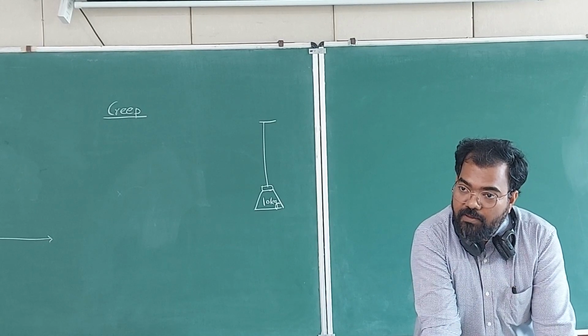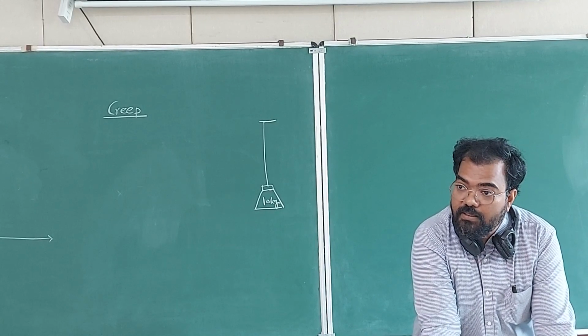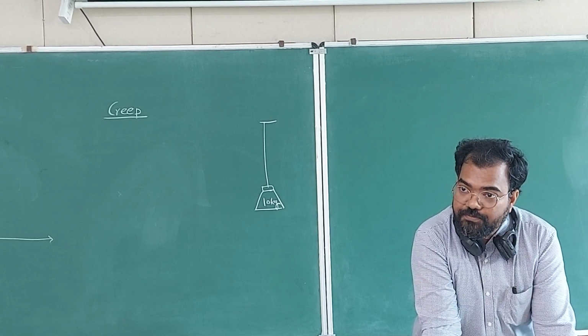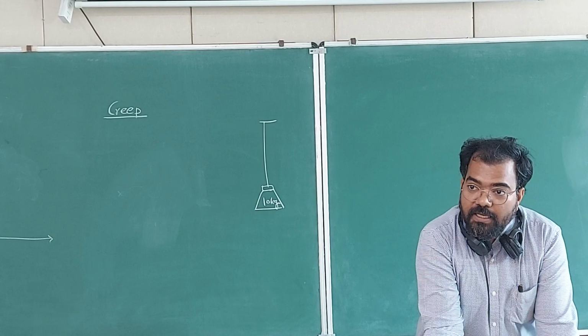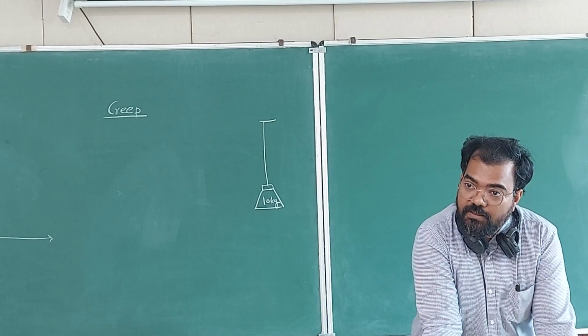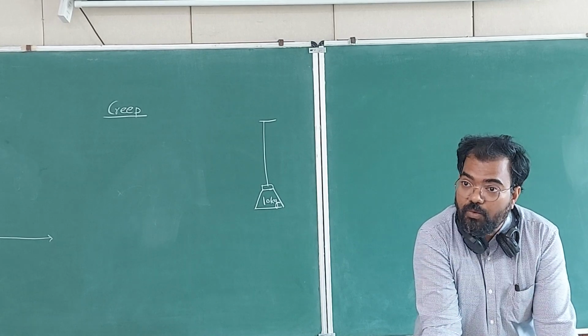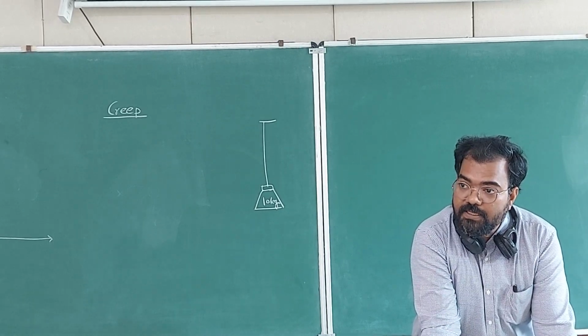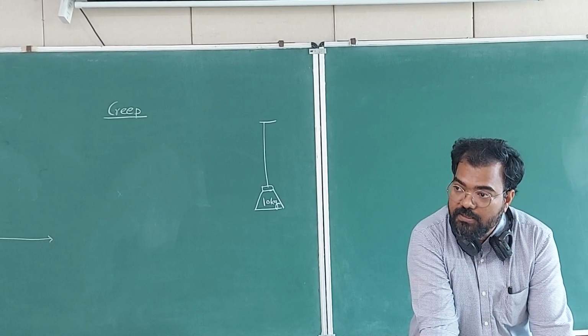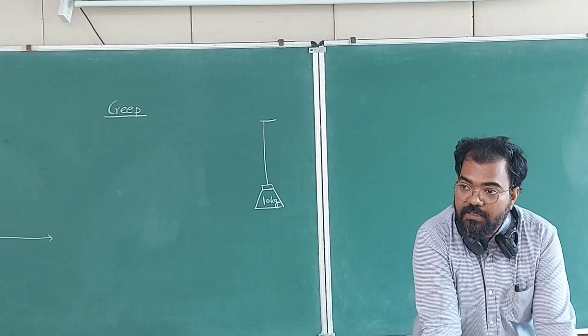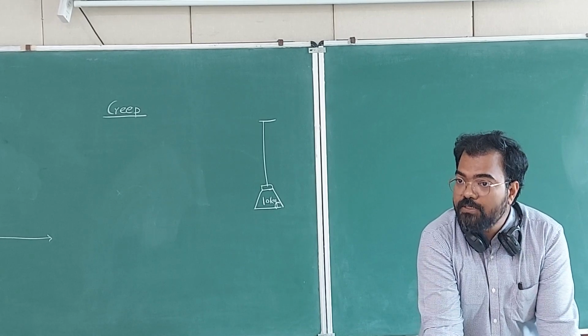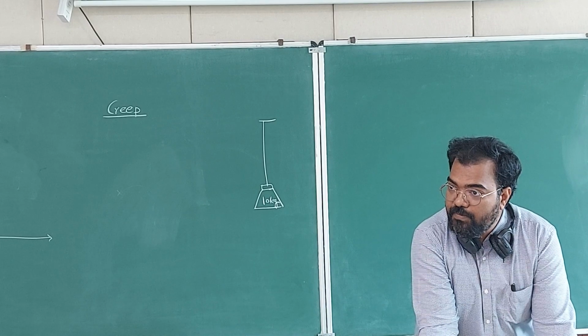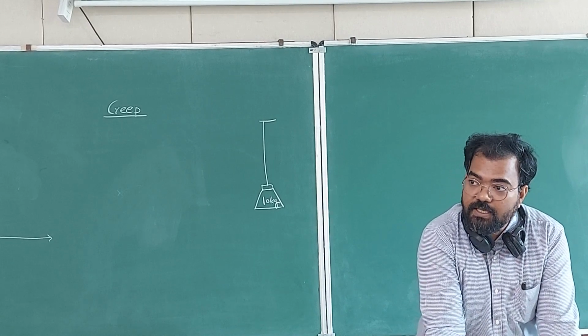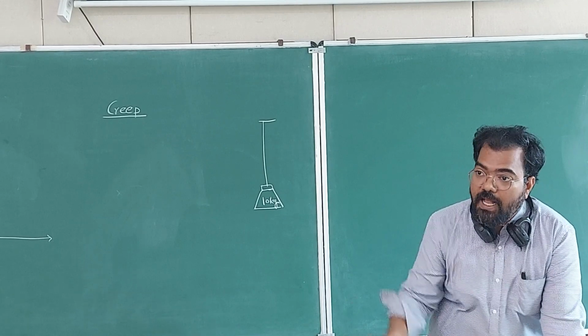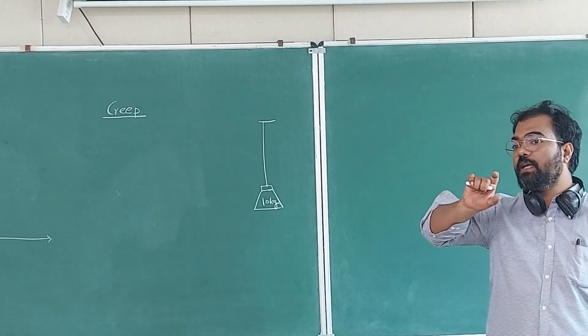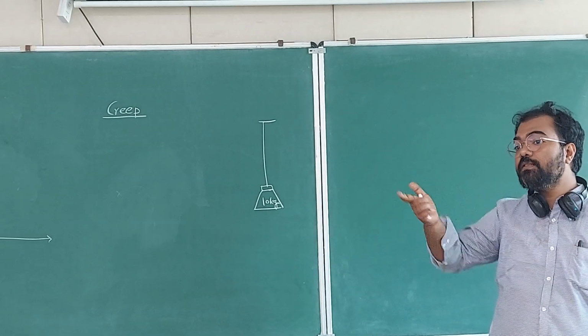Okay, and the second phenomenon will be happening when you facilitate diffusion. Okay, so vacancies do not need stress. That stress is there. They just have to go to the dislocation, and with increase in temperature, you are increasing the equilibrium number of vacancies in the system, and vacancies will move to the dislocation because there is a stress field there. Okay, and at the core of the dislocation there is a high stress field. So there is a gap, there is huge distortion at the core of dislocation, and the atoms can move through it. Also vacancies can move through it.